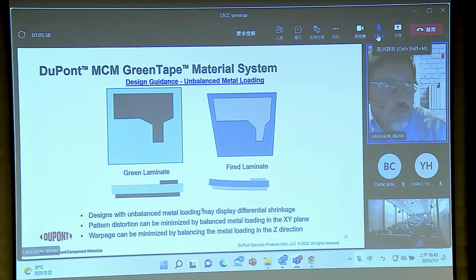And so when you design a part, it's important to think about the symmetry of your conductor designs. And we often see people put non-electrically functional metal patches in areas just to balance the metal, because if you have a very asymmetric part left to right in the XY plane or even top to bottom in the Z direction, that would cause warpage of the final part. And so if you can, the best you can, make your device function, but also think about balancing the metal on the front and the back side to minimize the amount of distortion, warpage, or camber that you would create by an asymmetric design.